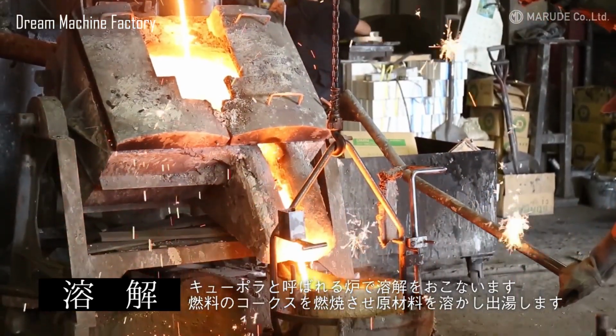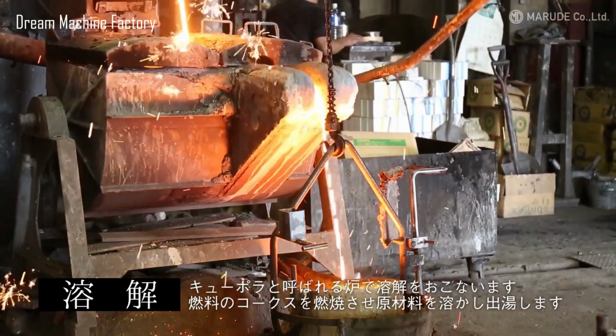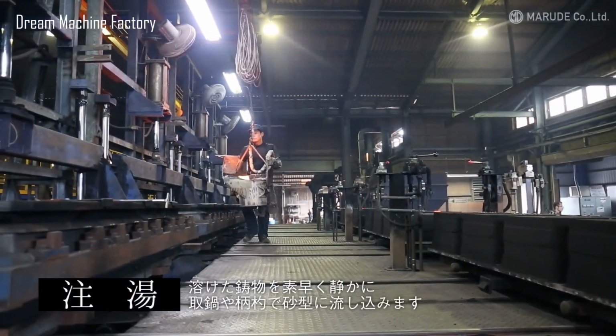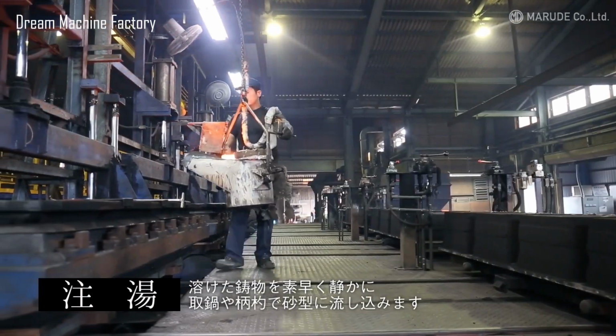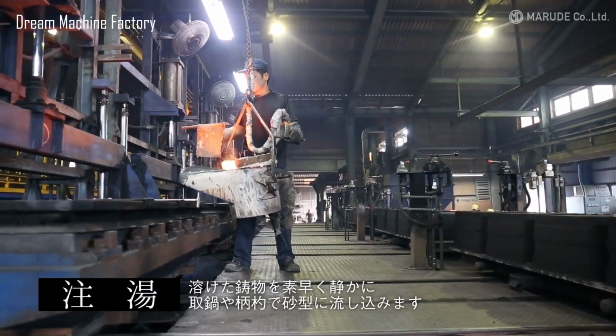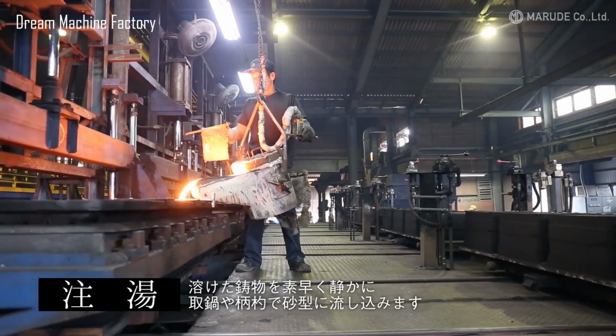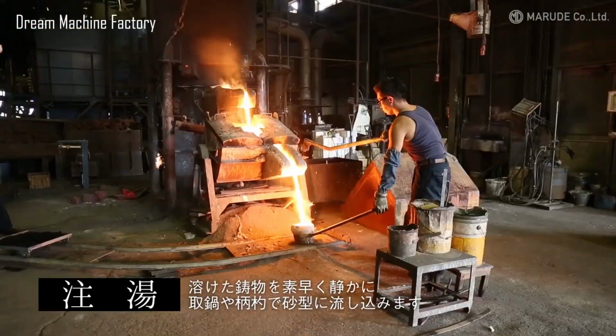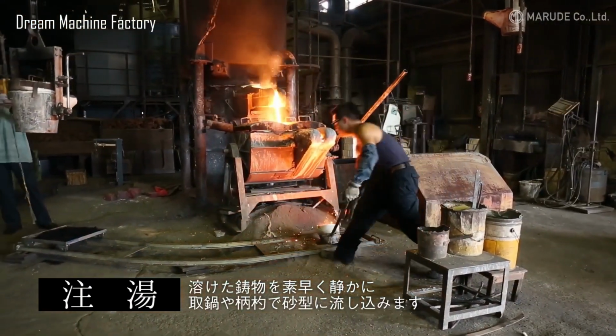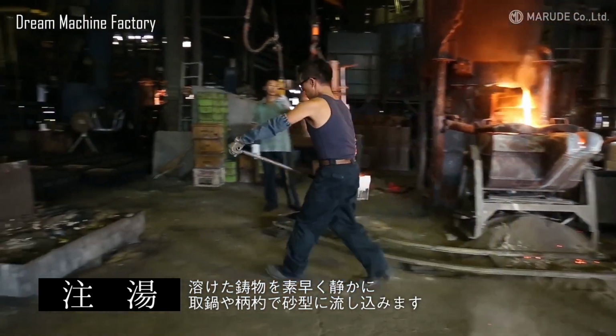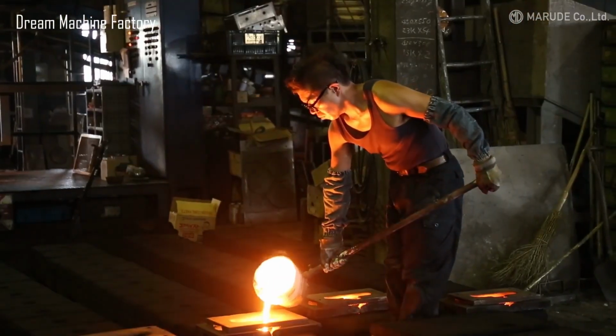Melting is performed using a furnace called a cupola. Fuel in the form of coke is burned to melt raw materials and prepare them for casting. Molten metal, heated to over 1,500 degrees Celsius, is carefully and swiftly poured into the prepared sand molds using ladles or scoops, ensuring a smooth fill without turbulence or air entrapment.